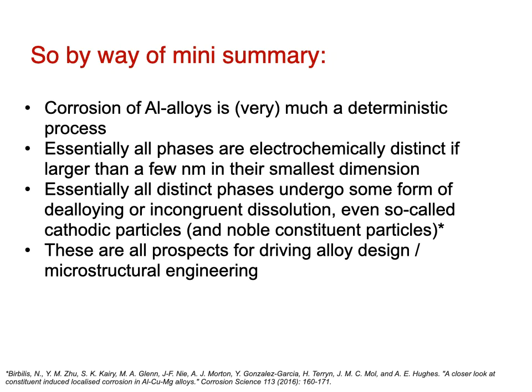All right, so look, by way of mini summary, corrosion of aluminium alloys is very much a deterministic process. Essentially, all phases are electrochemically distinct if larger than a few nanometers in their smallest dimension. Also, essentially, all distinct phases undergo some form of de-alloying or incongruent dissolution. And this has actually been true, I don't have the time to present in here, for even so-called cathodic particles and noble constituent particles that not only lead to corrosion of the adjacent matrix, but themselves, while serving as a cathode, undergo some incongruent dissolution. So these are all prospects for driving alloy design and microstructural engineering.